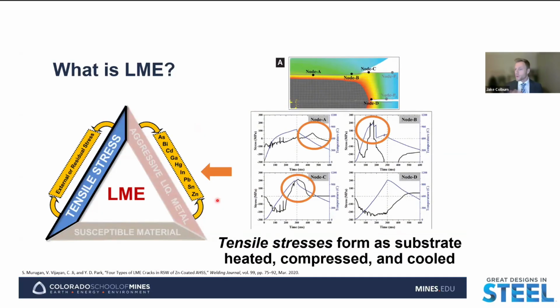For tensile stresses, we can have thermomechanical stresses that develop during the weld, which are the second leg of the LME components. Here on the right, we have a figure that shows FEA simulations of a weld electrode welding two workpieces. Below that, we have the stress and temperature profiles for different nodes throughout the simulation. As the weld time progresses, different locations see different thermal and stress profiles, but generally we see rapid increases and decreases in temperature, as well as tensile stresses developing during the weld cycle. As the substrate is heated, we have compression from the electrode, and then rapid cooling develops the thermomechanical stresses necessary for LME.